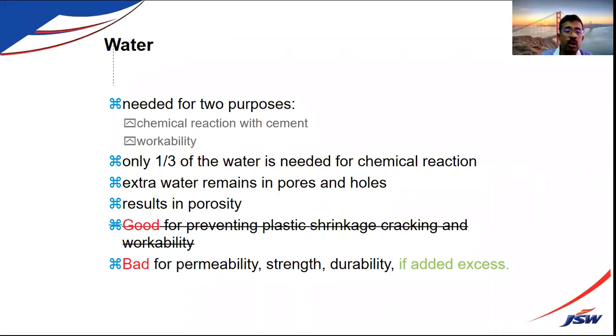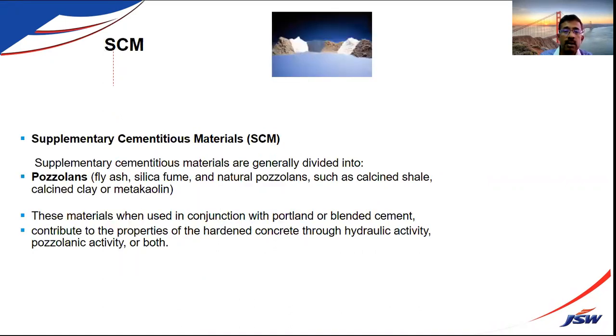So water is very much required, as I've already told you, both for chemical reaction and workability. SCMs, supplementary cementitious materials, are very important. We have fly ash, silica fume, and pozzolanas, which go with the concrete. So various percentages. We have made concrete using GGBS, M70, M100 grades of concrete, and various percentages we have used, starting from 25% to 70%.